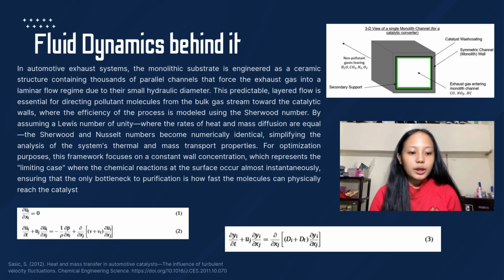Now for the clever part, the instant reaction rule. In our models, we assume a constant wall concentration of 0. This represents the mass transfer limited regime, where the catalyst is so efficient that the moment a molecule touches the wall, it's instantly converted. By modeling these channels as perfect squares, we can accurately simulate this limiting case. It proves that the only bottleneck for a total purification isn't the chemistry. It's simply how fast we can physically get the gas to touch the catalyst. It's a perfect balance of hydrodynamics and high-speed chemistry, all working together to keep the air clean.